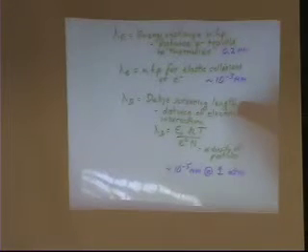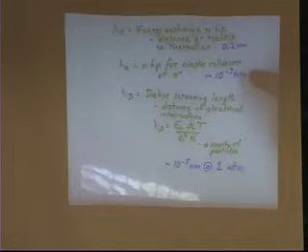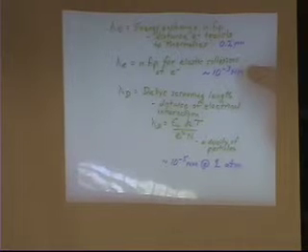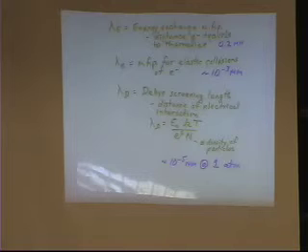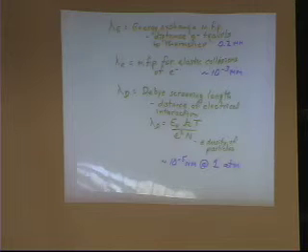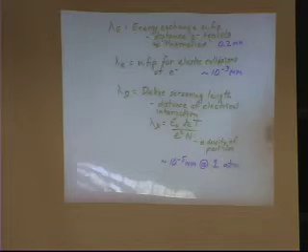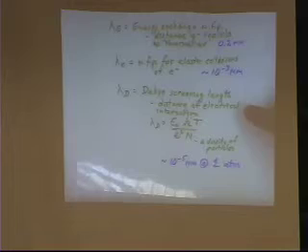But we did talk about different types of boundary layers. The thermal boundary layer is typically on the order of several tenths of a millimeter, but the distance over which the electrons collide with each other is on the order of 10 to the minus 3 millimeters. That works out to about 10,000 collisions before the electrons come into thermal equilibrium with the neutrals and the ions, which are so much heavier.